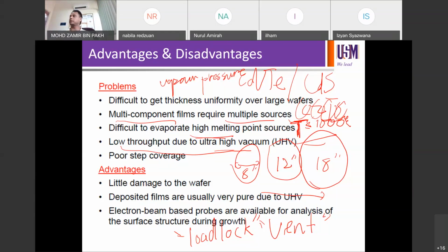Okay. But our system in the lab has no load lock. So when you don't have a load lock, you have to go through the process of venting the chamber from your base pressure, say -5, -7, back to atmospheric pressure. Open the chamber, remove the sample, put in a new sample, close it back, vacuum it back down to -5, -7, and do your processing.